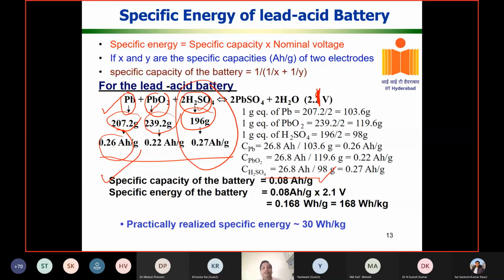If you multiply it with the voltage, that's your energy. Capacity into the voltage is your energy. If the voltage is 2.1 volt, you get 168 watt hour per kilogram. If you eliminate H2SO4, you get 240 watt hour per kilogram, but in practice it's 30 to 40 watt hour per kilogram. Very strange. This is because lead is heavy. And another important thing, I'll come to that actually.